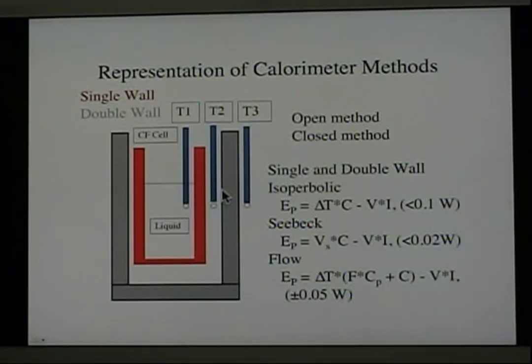A Seebeck calorimeter is similar to an isoperibolic calorimeter in the sense that this wall contains hundreds and sometimes thousands of thermocouples that are wired in such a way as to produce a voltage that is proportional to the temperature difference. So instead of measuring an actual temperature across the wall, a voltage is generated that is proportional to the temperature difference, and it is proportional to the average temperature difference throughout the wall structure itself. As a result, it's more accurate than simply measuring the temperature at a few places.